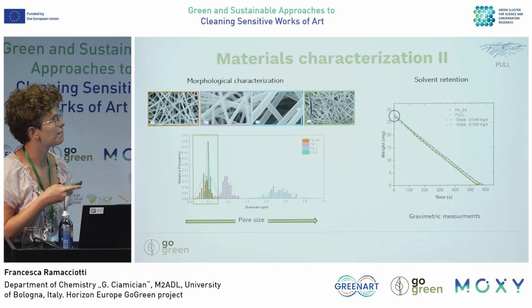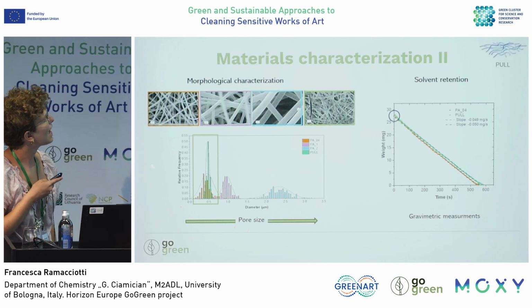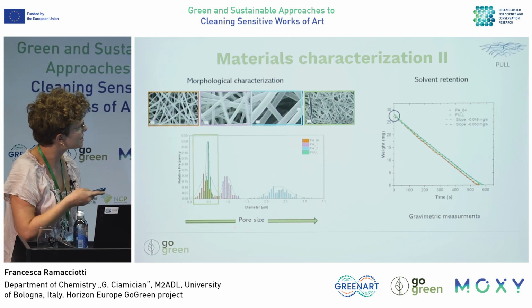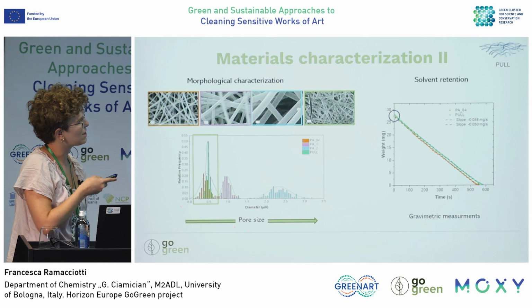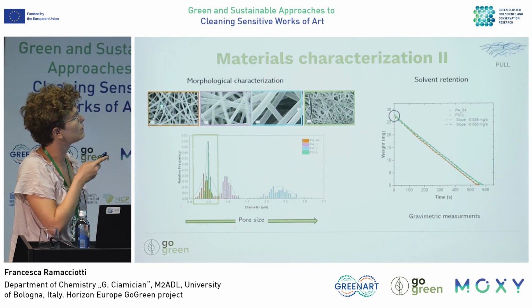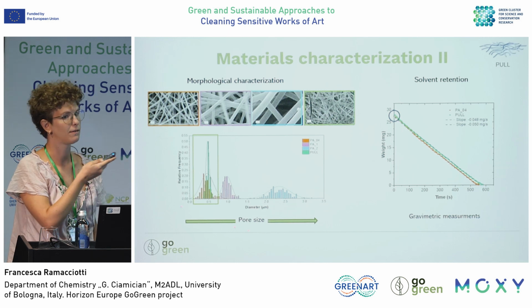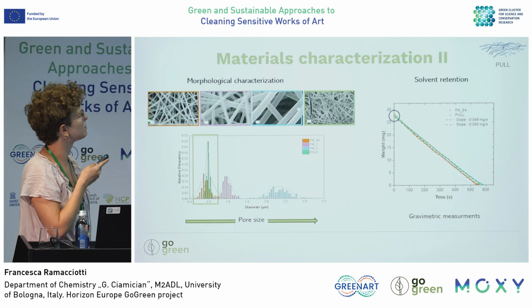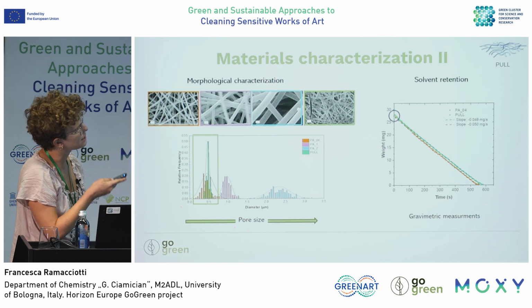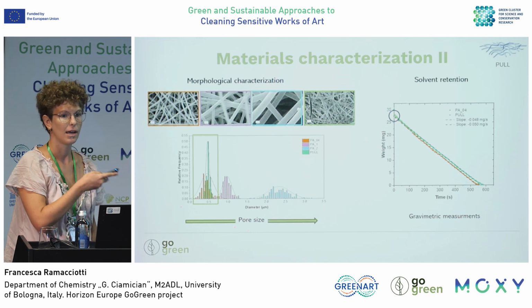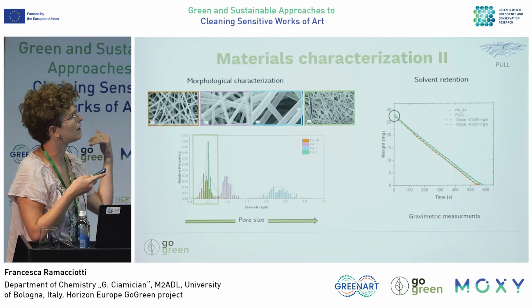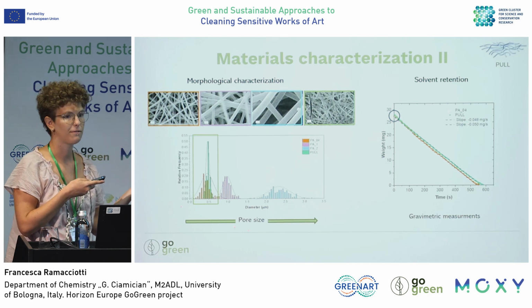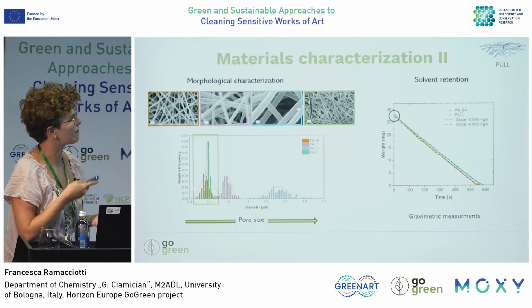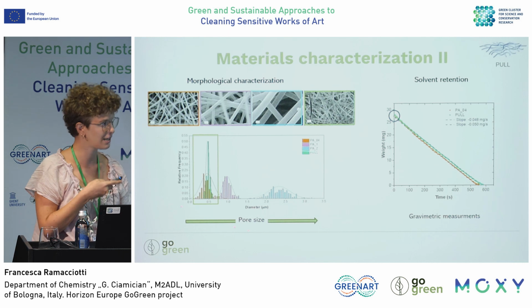As I was saying, it is a bio-based polysaccharide, and we produced it with the same fiber diameter and similar pore size to the polyamide 6,6 that we observed was the best one in terms of cleaning. And as you can see also, the solvent retention is unchanged, meaning that the chemical properties of the fibers are not affecting the evaporation and retention of the solvent.